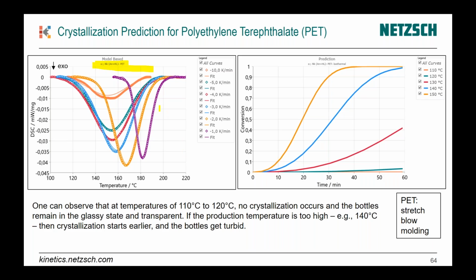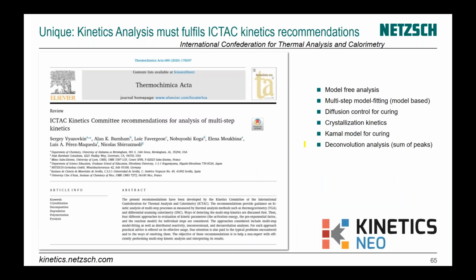And now this modeling is okay, and we can see what happens during stretch blow molding. It's isothermal, about 1 hour, we make simulation for 1 hour near temperatures maybe 110, 130, somewhere in this range. We see that for low temperature, almost no crystallization happens, material is transparent, our bottle is transparent. For higher temperature, somewhere here, there is crystallization and material is not transparent anymore.